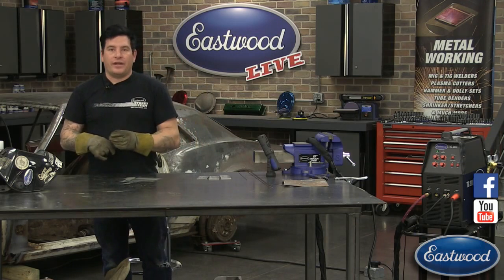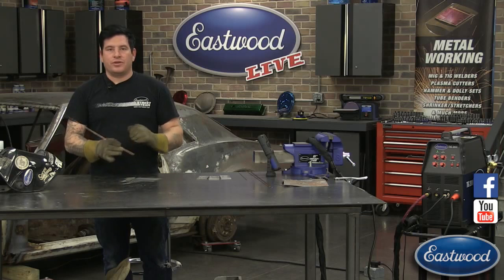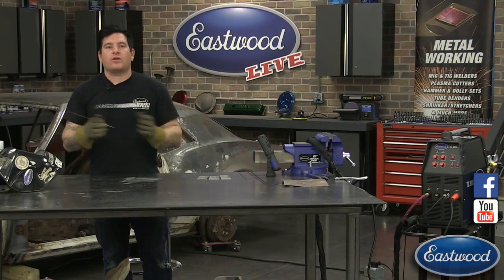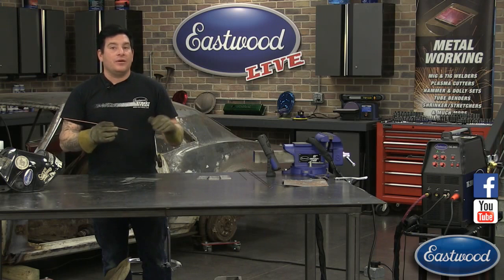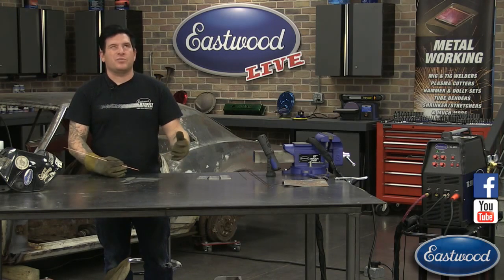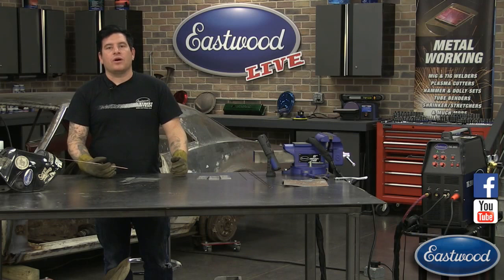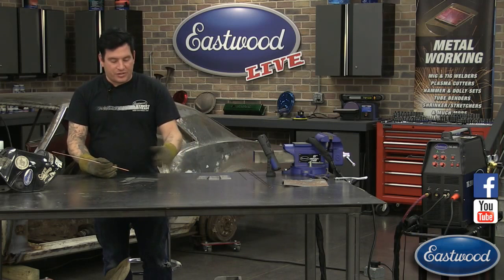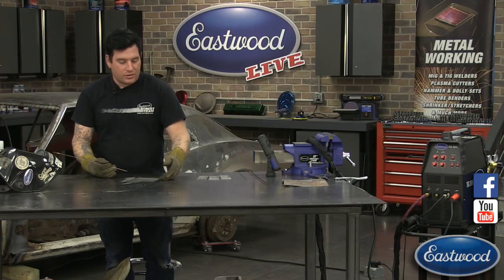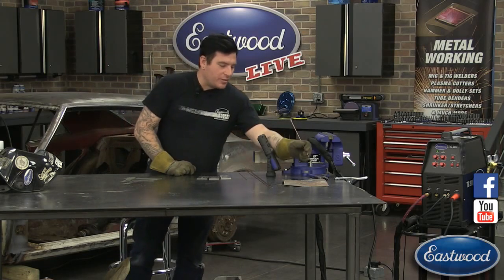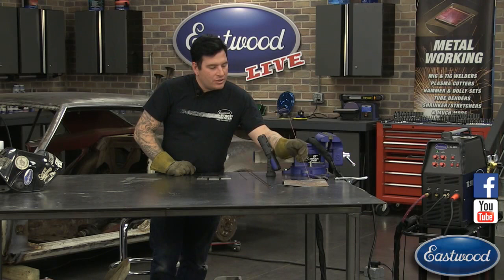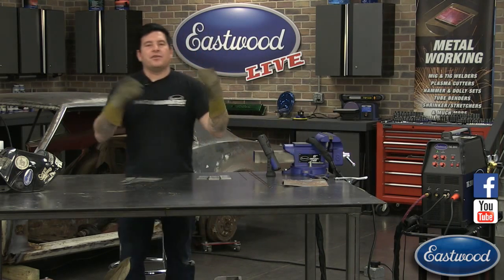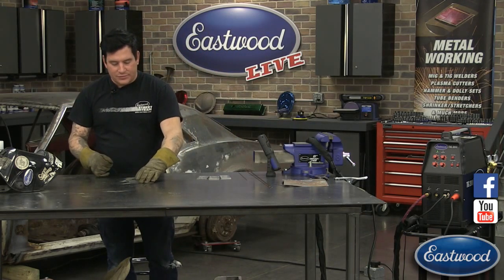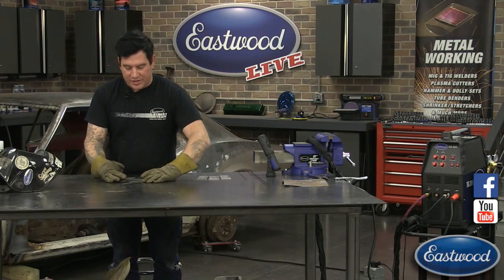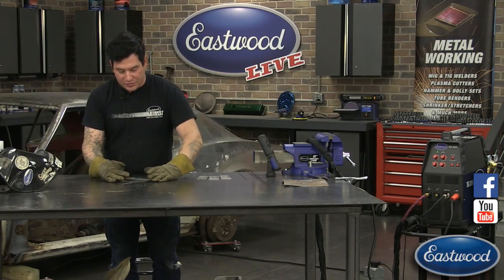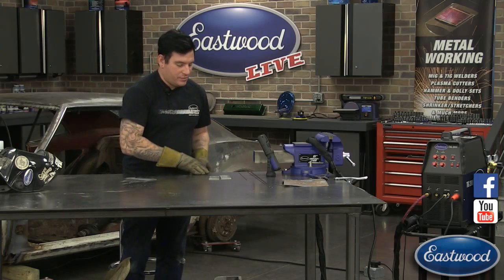You'll know it when you're welding, because when you're TIG welding, it's really smooth, controlled. There's no popping, there's no sparks, nothing like that. So if you're hearing or seeing popping or spatter, something's wrong. It's probably dirty. There's probably some kind of contaminant, or you don't have enough gas flow. So that's a good question. I tried to do some on this sheet metal here, but it's not enough to be able to see it on camera. It's not as dramatic as I was hoping. So that's my best description. But you'll know it. If it's popping and carrying on when you're TIG welding, you got a problem.